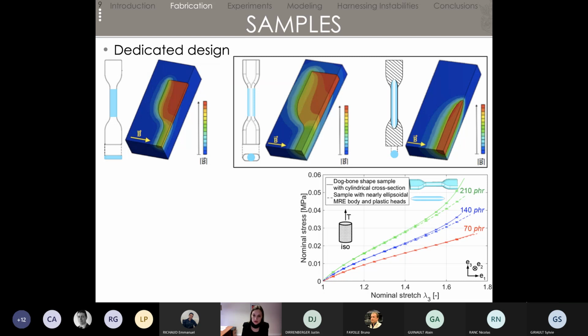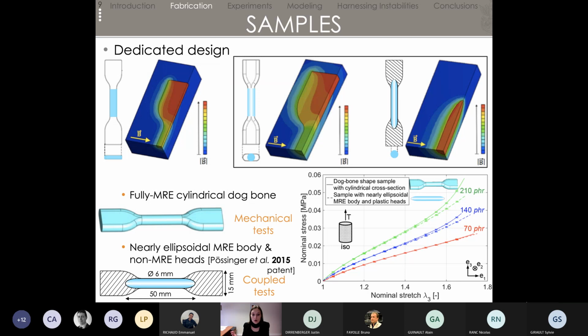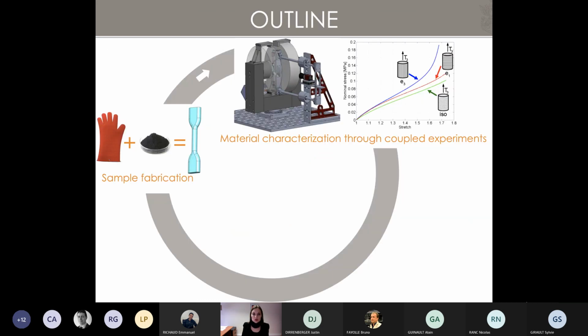So in which case we cannot use the sample with the ellipsoidal body to do mechanical characterization above a certain stretch threshold. So we solved this somehow by deciding to take a fully MRE dog bone shaped sample for mechanical tests, and then for the coupled test where magnetic field is on, we will use the other sample with the ellipsoidal magnetorheological elastomer body and the non-MRE heads. So that's all for the tricks about the sample. So now I'll switch to our setup for magnetomechanical characterization.